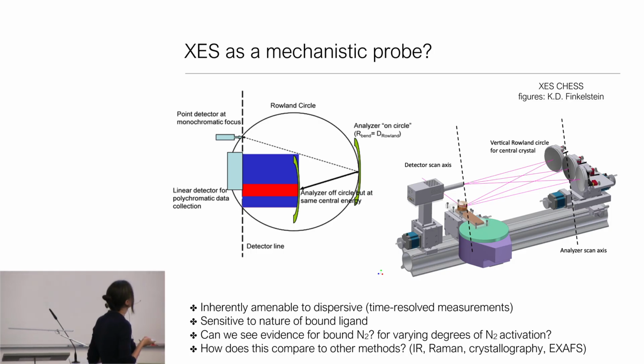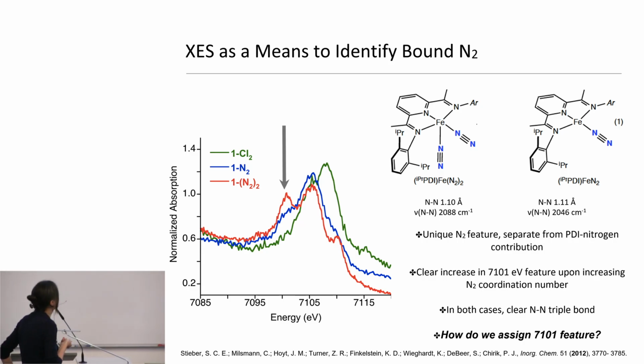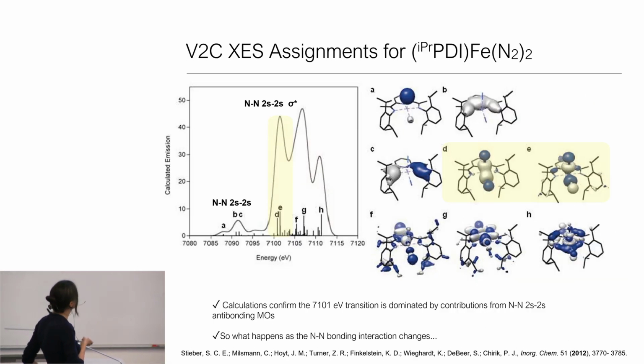probe reactivity. And so we did this by first asking if we could see something like NN bond activation using valence to core. And so we started with these samples that had chloride. You can see the green is a PDI chloride. And if we add 1 or 2 nitrogens, there was a feature actually growing in here, which we surmised must be due to coordinated N2. And then we used ORCA to assign this, and what we found is that this feature was due to the 2s sigma star interaction. So we could actually look at and see what that happens.